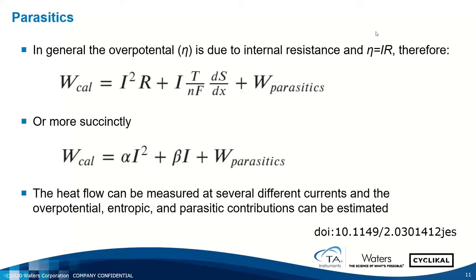So typically the overpotential is caused by internal resistance, and so the overpotential, V equals IR, will be a function of the current times the resistance. And if I substitute this into my equation, I get an I squared here times internal resistance. And so I notice that I have a second order polynomial in terms of current corresponding to my heat, right? So I have second order here, linear term here, and then I have a constant that's independent of current. And this will apply in some situations where I have a very well-behaved cell. And if I do have that, I can cycle my cell at different currents and extract the function, fit this equation, and extract the complete functional form of my heat flow coming from my calorimeter, and then get a quantitative measure of internal resistance, entropy, and parasitics. And the reference here gives an example of that.